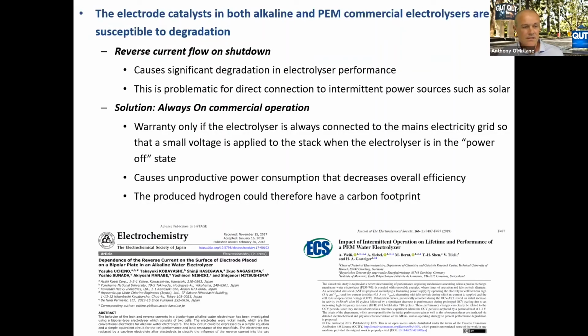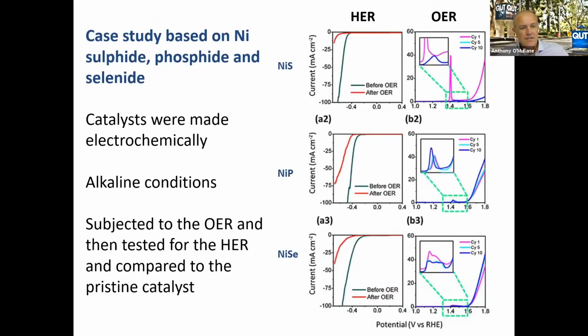As we saw in that example, when we oxidized our iron-based material, it was very detrimental to the hydrogen evolution reaction. So this raises the question: if we use these metal chalcogenide species as a bifunctional catalyst, is it really bifunctional? So we did a case study based on nickel, nickel sulfide, nickel phosphide, and nickel selenide.